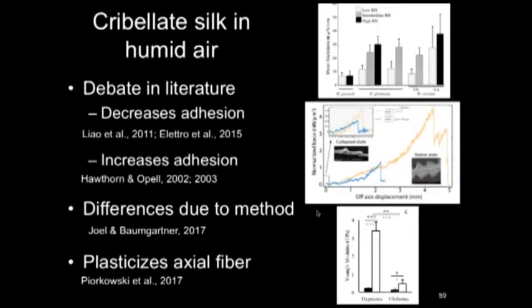So that may be what the differences in methods between these studies may have been what led to these results, meaning that in wet conditions such as the humidity of caves and sort of subtropics and wet nighttime at dew point may increase adhesion, but in rainy days it may cause collapse and therefore non-functionalization of webs.